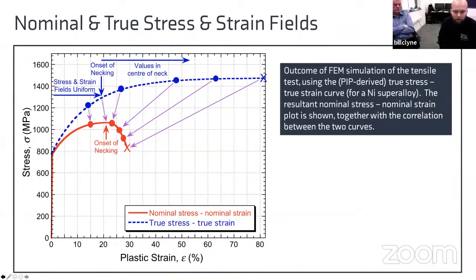neck forming. If your question is related to porosity and voids in additively manufactured materials, certainly they can act to promote fracture prematurely, so maybe earlier in the necking, once the material has necked, or maybe even before necking, and that is something that we can't capture with indentation. The stresses in general are compressive, and therefore we're not stimulating any fracture during the indent. But there is no consideration of voids in the simulation, because actually you predict the neck without any voids. That's just a continuum.